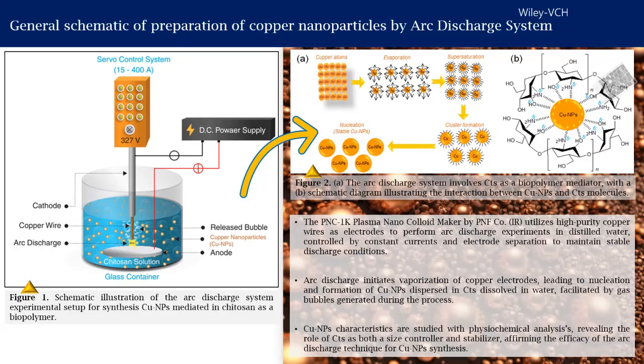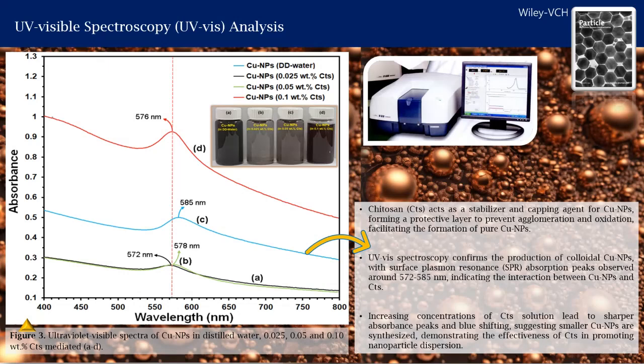The general schematic of the preparation of copper nanoparticles showed that the plasma nanocolloid maker by PNF utilizes high-purity copper wires as electrodes for arc discharge experiments in distilled water, controlled by constant currents and electrode spacing. Arc discharge vaporizes copper electrodes, leading to nucleation and formation of copper nanoparticles dispersed in chitosan dissolved in water, facilitated by gas bubbles. Physiochemical analyses reveal chitosan's dual role as a size controller and stabilizer, confirming the efficacy of arc discharge for copper nanoparticle synthesis.